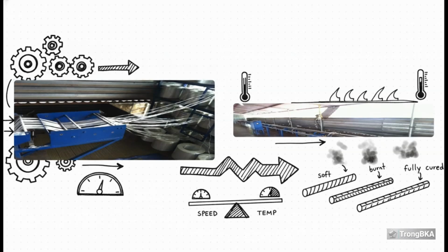Just to ground this theory in reality for a second, here are actual photos from a production line. On one side is the mechanical feeding and pulling system managing the raw glass threads. On the other, you've got the massive 12-meter-long thermal heating tube. The absolutely crucial point here is balancing your variables. If you pull the material too fast, say faster than 1 meter per minute, it simply won't cure fully in the middle.